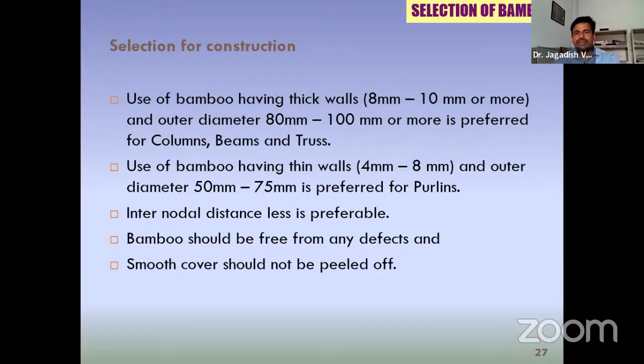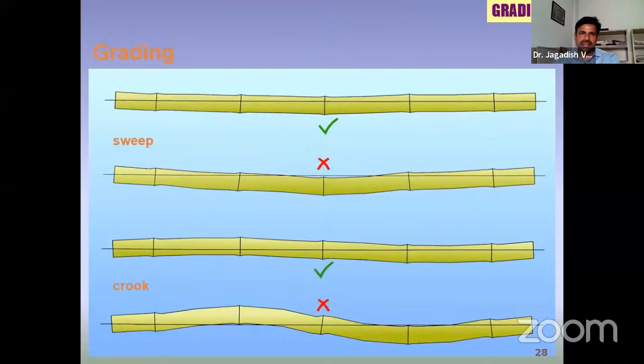Thin-walled bamboo you use for purlin purposes. For purlins, you require only 2 inch to 3 inch bamboo, and a smaller internodal distance is preferable. Also, the smooth outside cover of the bamboo is a silica layer. You should not peel it off. It protects the bamboo from external weathering.